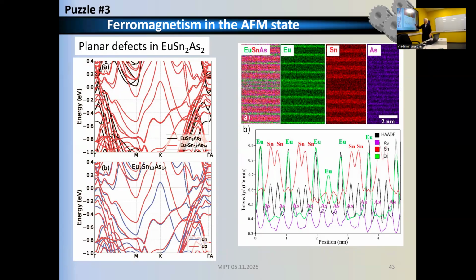Nikita Pavlov did these calculations and found how the energy levels change in the recalculated structure for this supercell for the transition layer. But experimentally, we also were able to do the nanoscale elemental analysis for europium, for tin, for arsenic, and this confirms what I showed in the previous picture, that tin is almost vanishing in the defect layer.